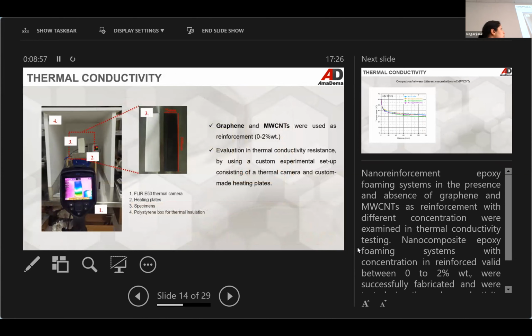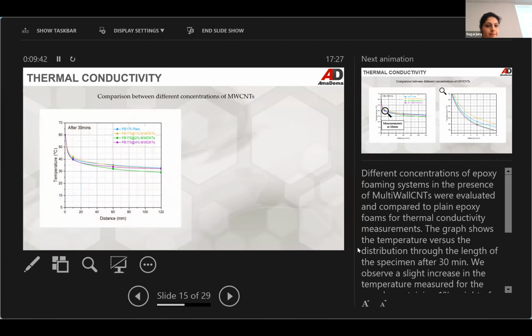The next thing we wanted to check was the thermal conductivity of the resulting epoxy foams. We wanted to see how they behave when they're heated, and we used a homemade system consisting of a thermal camera and heating plates, as you can see here. We're holding the sample with these heating plates in an insulated environment. So we heated the sample and investigated the temperature along the length and, of course, along the time of the experiment. For this type of experiments, we've used graphene and multi-wall CNTs, since these are conductive nanoparticles.